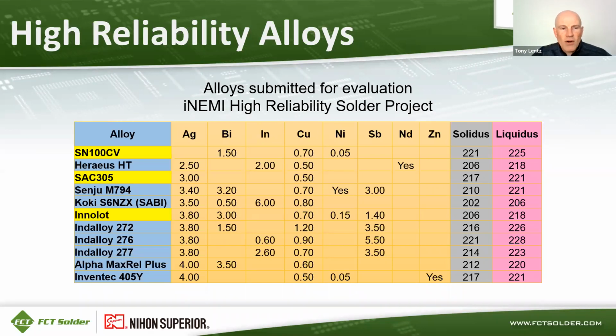This is a table full of high reliability solder alloys that were submitted to an iNEMI solder project. I've highlighted 3 of these alloys that I'm going to be talking about in detail throughout this presentation. The first one on the table is SN100CV, which does not contain silver, but it contains bismuth, copper, and nickel. And that's the only alloy on this list that does not contain silver. Then there's SAC305, which is our baseline lead-free alloy that's most commonly used. And of course, we know that has 3% silver. And then if you look down a little farther, there's Innolot that's highlighted, which is a very popular automotive alloy. And that has several different elements in it, including 3.8% silver, 3% bismuth, 0.7 copper, 0.15 nickel, and 1.4 antimony. So it's quite the mixture of alloys, but it does seem to function very well, especially in under the hood